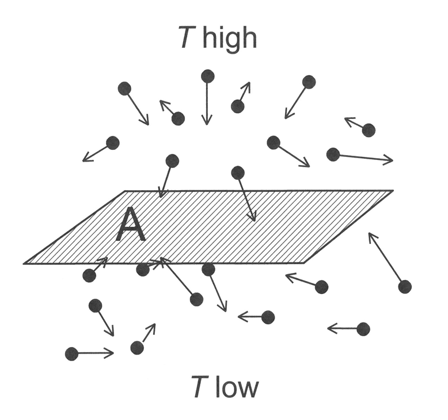In metals, heat conductivity is primarily due to free electrons. Following the Wiedemann-Franz law, thermal conductivity of metals is approximately proportional to the absolute temperature, in kelvins, times electrical conductivity. In pure metals, the electrical conductivity decreases with increasing temperature and thus the product of the two, the thermal conductivity, stays approximately constant. However, as temperatures approach absolute zero, the thermal conductivity decreases sharply.